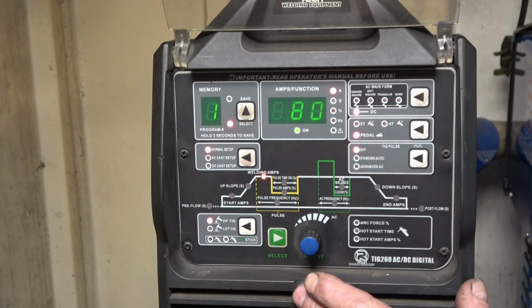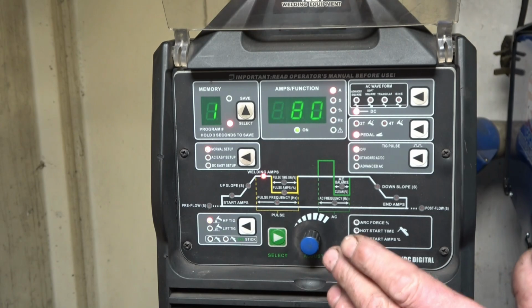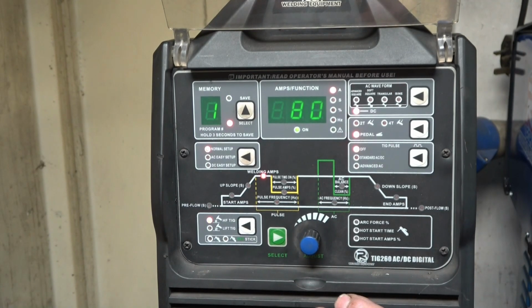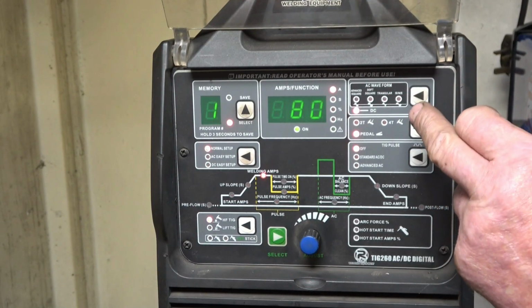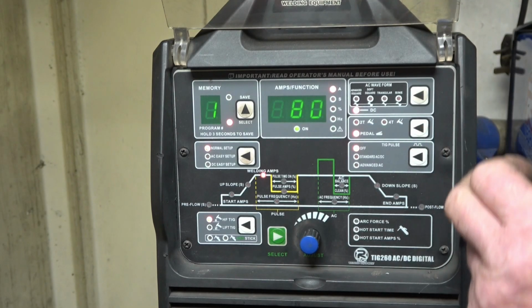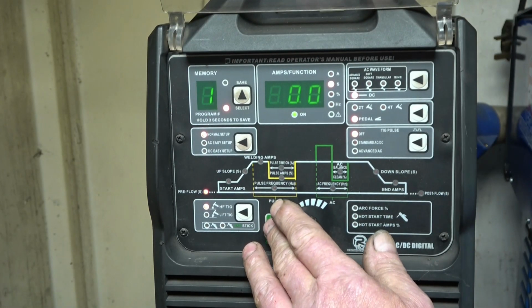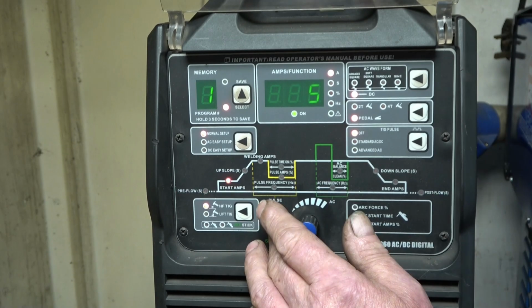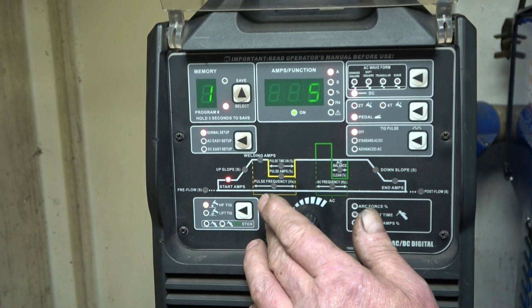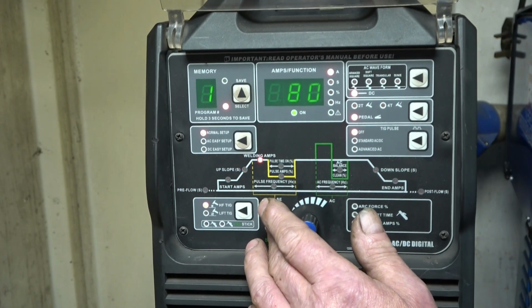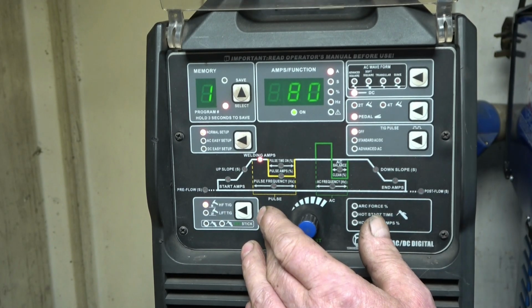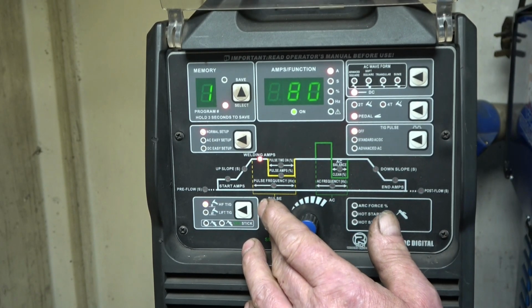This is program one on this machine. It's a basic DC welding setup. So we're on DC pedal and all the pulses are turned off. I've got no pre-flow because I'm using a pedal. Start amps is as low as it'll go at 5, no upslope. Main welding amps, I've got it set at 80, it'll be more than enough for the job I'm doing.